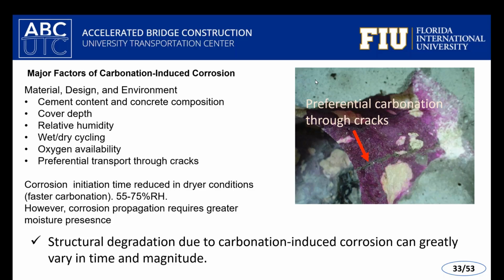So there can be a path by which that rebar sees an environment that has carbonated concrete, associated with a lower pH, where active corrosion can occur. So even with high performance concrete, there can be some concerns for carbonation that may appear. And again, we'll allude a little bit to UHPC and how that may be beneficial to mitigate some of these effects. One important thing to mention for this type of corrosion is that the degradation can vary greatly.